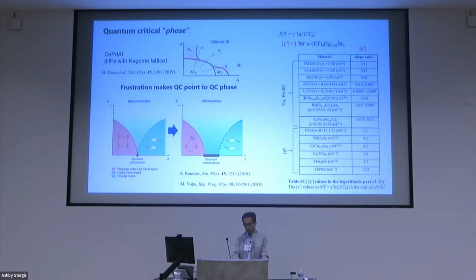Okay, and this coefficient of the linear term is called gamma prime. Gamma prime characterizes the strength of the quantum criticality. In our case, gamma prime is about unity. And these are the gamma values for iron superconductors, and then heavy electron systems. The heavy electron systems show very high quantum criticality. Our system is between the heavy electron systems and the others. Maybe this is correlated with the Fermi energy or inverse bandwidth, I think.